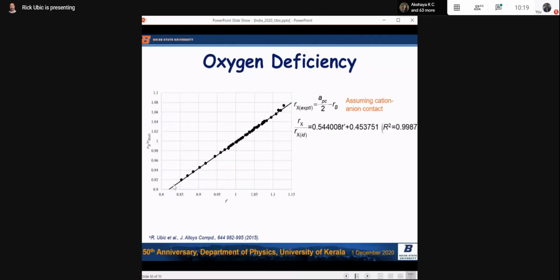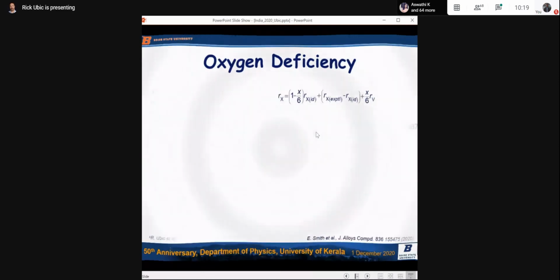And we have this, all right? So this is Rx over Rx ideal. Again, if Rx were equal to Rx ideal, this would just be a line at 1. But it's not. It's still a line, but it's got this positive slope, just like it had before. And remember, the last model had this. These are essentially the same equations. We're using a different data set, so the equations come out very slightly different, but the actual values come out virtually identical. So that's the same equation.